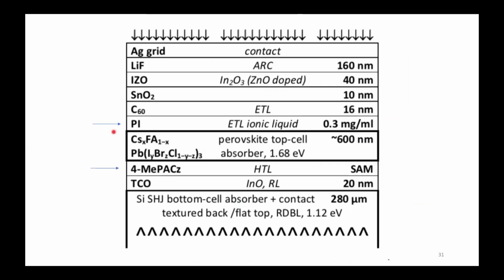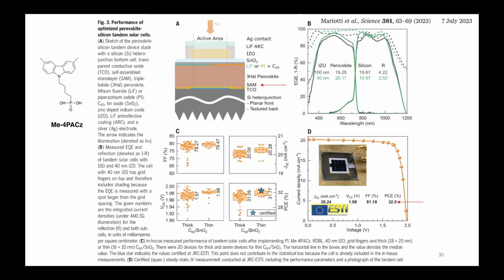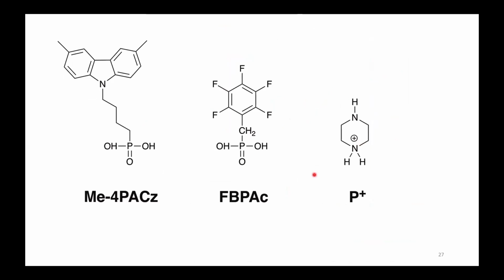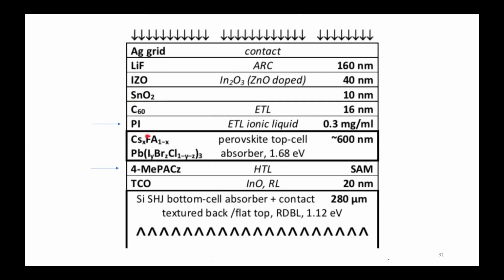Here we have the perovskite. You see, it is containing cesium, formamidinium, some iodo, some bromo, some chloro. They actually don't know exactly how much is in there, about 600 nanometer thick. On top, we have this piperazinium iodide. This molecule, as the iodo salt, is an ionic liquid and is good at transporting electrons. It is a donor acceptor system. This part is electron rich, this part is electron poor. Piperazinium iodide is the electron transport layer on top of the perovskite.